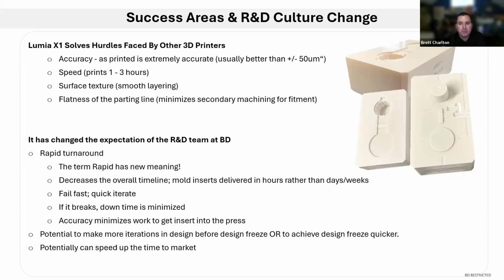In all honesty, before discovering this application with the Asiga Lumia X1 coupled with the BASF material, we had essentially given up on producing molds using SLA or DLP processes for a myriad of reasons. SLA molds typically take around 16 to 24 hours to produce and required extensive post-printing adjustments for proper fitment. And the materials available to those legacy technologies often yielded only a few usable shots before failing.